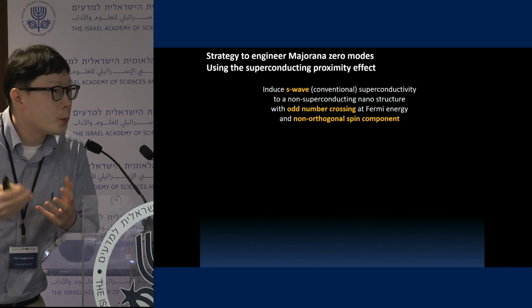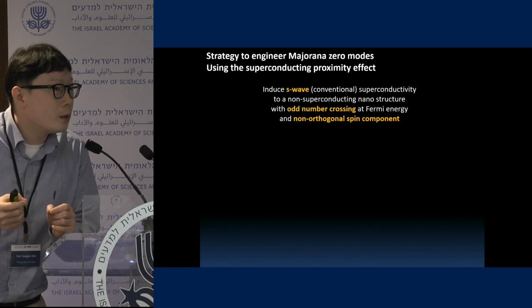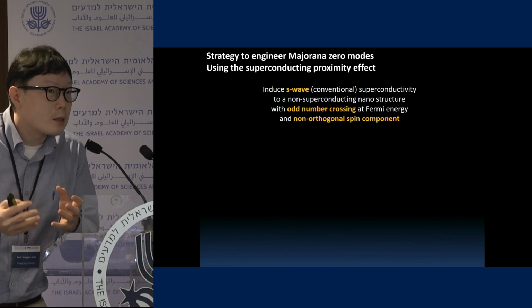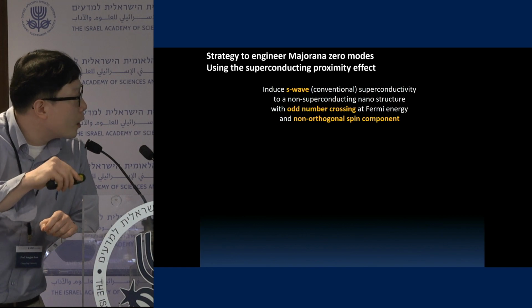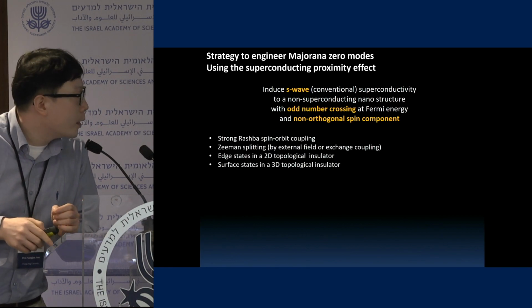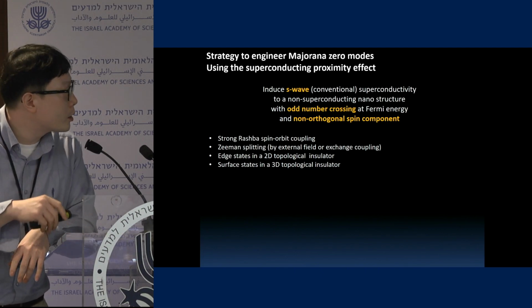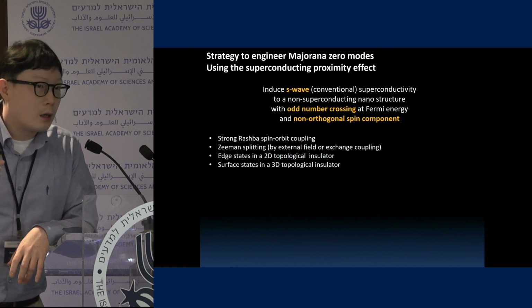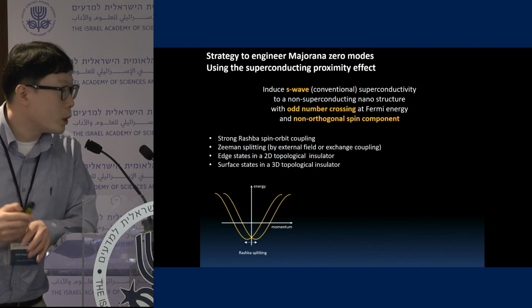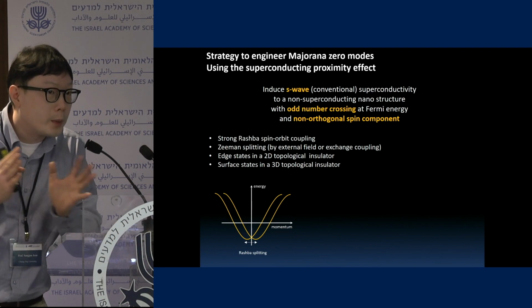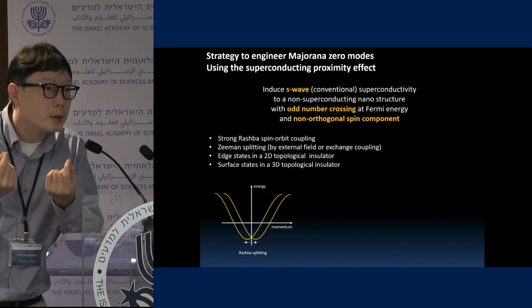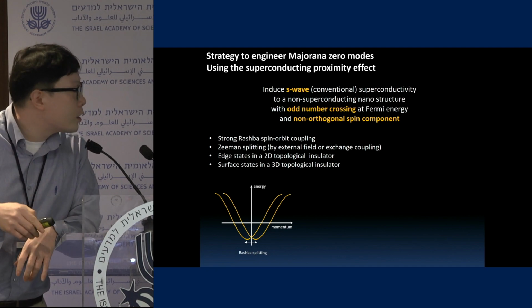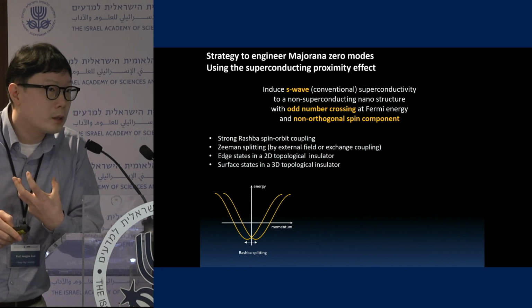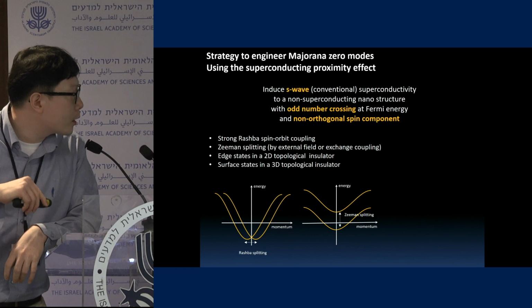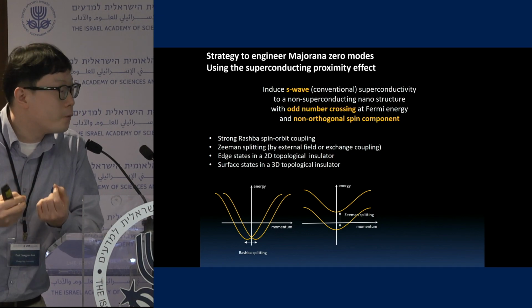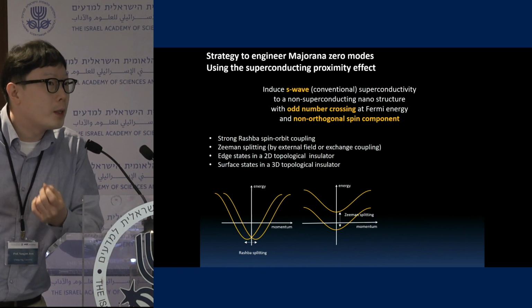And at the same time, if you want to open a gap, I will show you later, then the spin of the states has to have non-orthogonal components in it. Okay, so these are some ideas we got from the theoretical proposals. And then to get into real materials, we have to consider these things. The first thing is strong Rashba spin-orbit coupling. So we know that if you have spin-orbit coupling, in momentum space the spin degeneracy is lifted. And the other thing is using Zeeman splitting, basically the external field and the exchange coupling, so that energetically the degeneracy is shifted. By doing this, in principle, we are able to get some spinless systems.